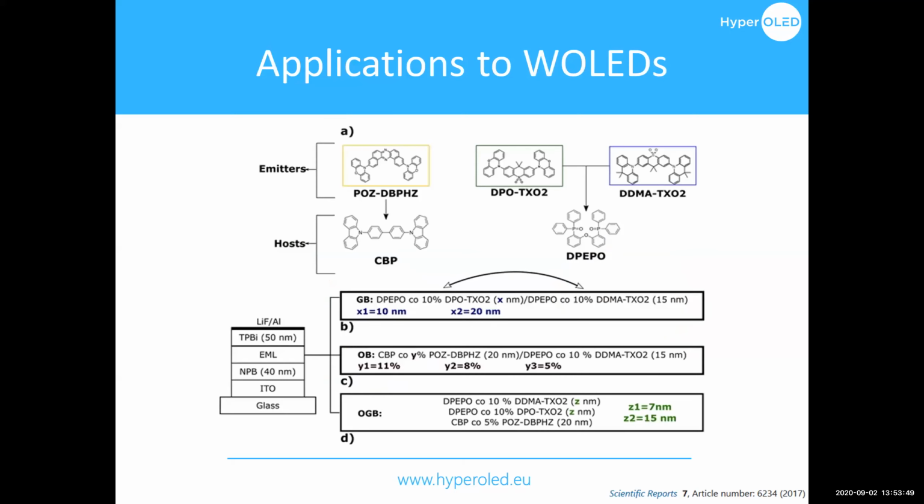Now, if you wanted to do that, though, there are some methods that are more complex, and there are other methods that are less complex. One of the more complicated ones, but ultimately the one that industry kind of wants to pursue, is mixing together different red, green, and orange, or red, green, and blue, or blue and orange TADF emitters together or in separate layers inside an LED. The issue with this, though, is that there's a huge amount of optimization that needs to happen before you can get a good white OLED based on co-evaporation of all the different components into the same emissive structure.